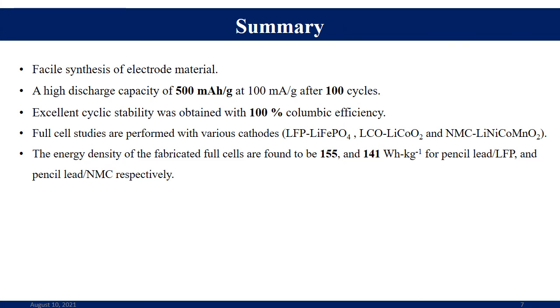We have demonstrated an inexpensive and facile synthesis route to prepare a graphite silica composite anode. Also, the pencil lead anode showed an enhanced electrochemical performance even at high current densities due to the presence of SiO2 in graphitic domains. Further, full cell studies were also performed with various commercially available cathodes to examine the practical applicability of such a low-cost 4B pencil-based anode material.